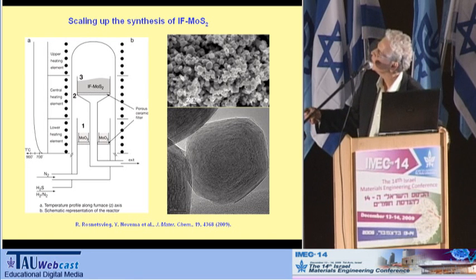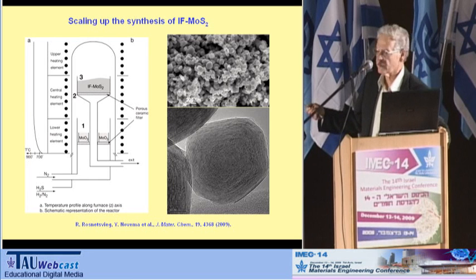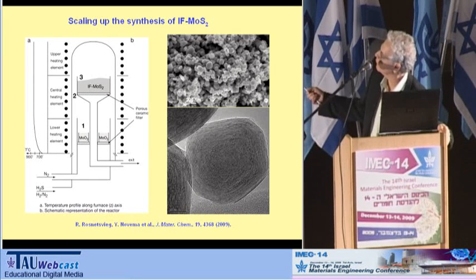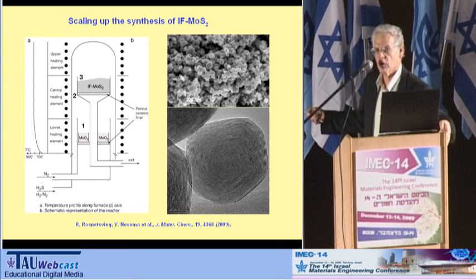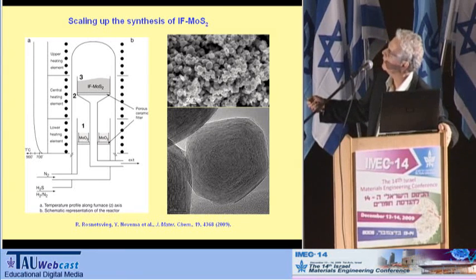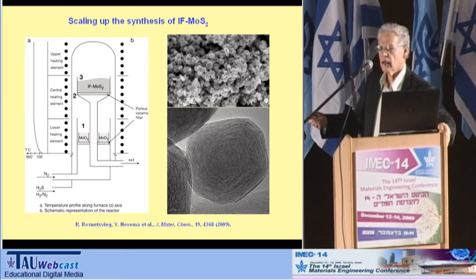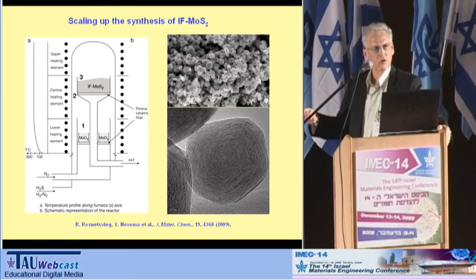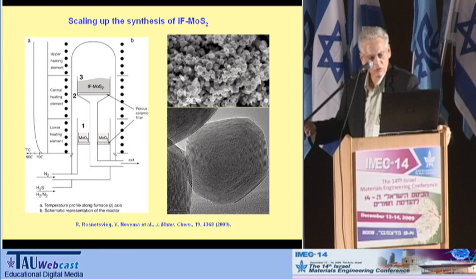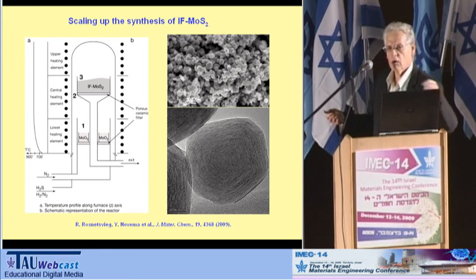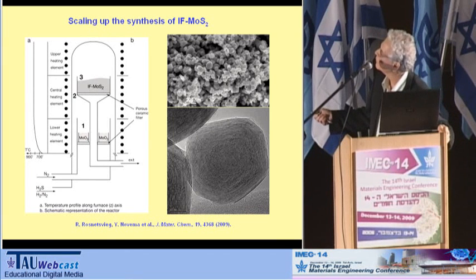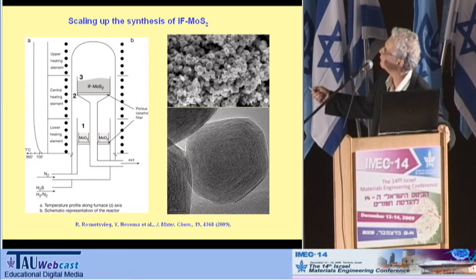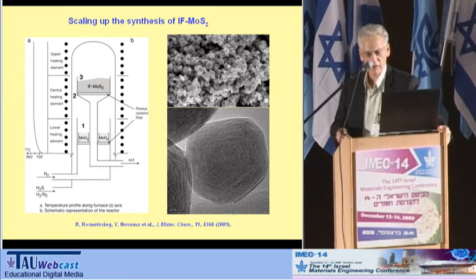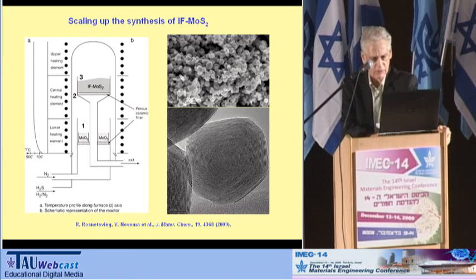These nanoparticles then react with hydrogen sulfide around this position, and in a matter of seconds they are covered by 2 layers of molybdenum disulfide on top of a molybdenum oxide core. Then they land on the filter here, and gradually, by a diffusion-controlled reaction, convert from molybdenum oxide to molybdenum disulfide. They grow quasi-epitaxially inwards: the sulfur diffuses in, the oxygen diffuses out, and they grow layer by layer until they form this closed structure, made solely of molybdenum disulfide.